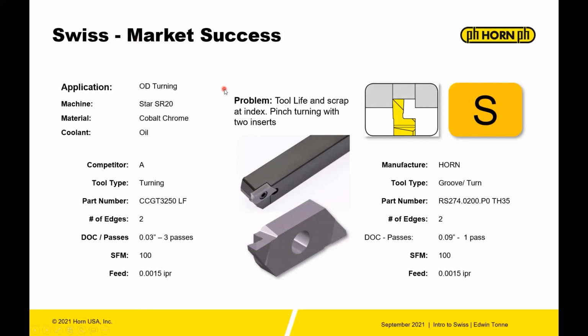All right, now let's talk about market success, just showing you an example of how Horn tools can shine. So this is an OD turning on a Star SR20. The material is cobalt chrome and the coolant is oil. So in the original process, the customer was using a CCGT and using a pinch turning process. So they're using 2 inserts. These CCGTs have 2 cutting edges. So they were using 30 thousandths depth of cut with 3 passes to achieve 90 thousandths, 100 SFM, and 1 thou 5/10 inch per rev.